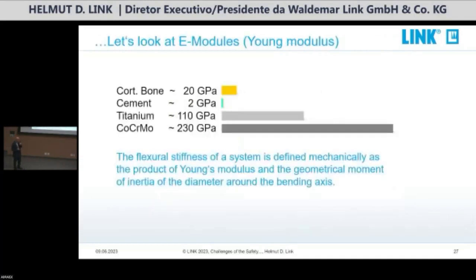When we look at the Young's modulus: cortical bone, 20 gigapascal; cement, 2 gigapascal; titanium, 110; cobalt chromium, 230. The rule is that the flexural stiffness of a system is defined mechanically as the product of Young's modulus and the geometrical moment of inertia of the diameter around the bending axis. What does that mean? Sounds very complicated, but